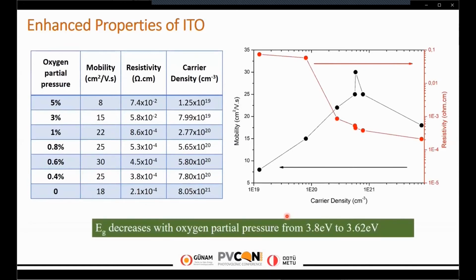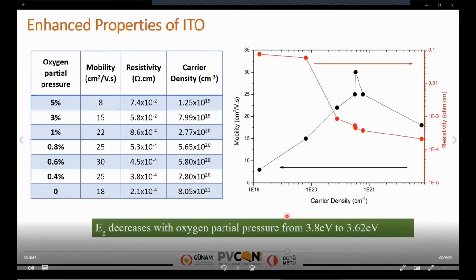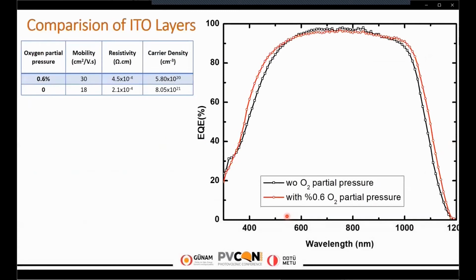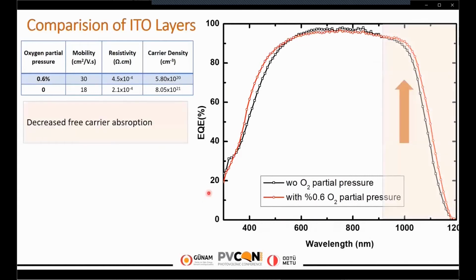Band gap decreases with increasing oxygen partial pressure from 3.8 eV to 3.6 eV. When we insert these two ITO layers, one with 0.6% oxygen partial pressure, one without oxygen partial pressure, you can see the quantum efficiency result of the silicon heterojunction solar cell on the right-hand side. Due to the decrease in the free carrier density of the ITO layer, the spectral response improved and free carrier absorption decreased.